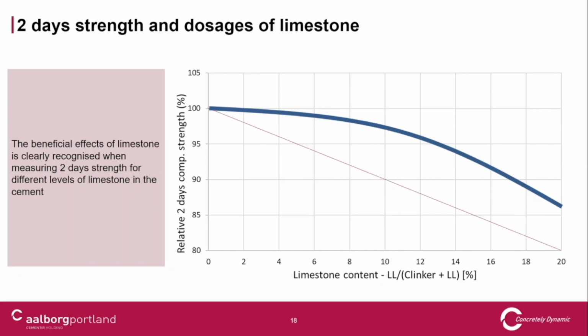What should be expected if there was no effect of the limestone is, of course, a gradual decrease in strength corresponding to the amount of replacement, the amount of limestone put in. But that is not what we see. We see that the strength is almost not influenced with low amounts of limestone, and it's only up until around 10% that we really see a decrease in 2-day strength.